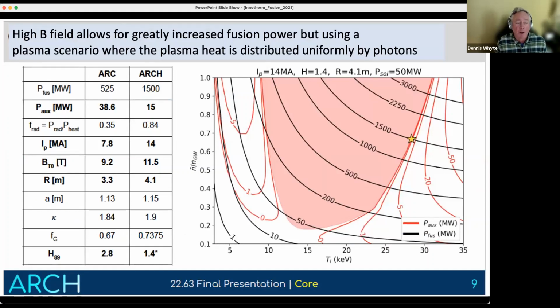Where we ended up was, there were some other things that happened in terms of the fusion design. We decided we had to eliminate any concentration of internal heating on the surfaces from the plasma removal, so we got rid of it. The way we got rid of it was that being able to access higher magnetic fields allowed us, very non-intuitively, to intentionally degrade the plasma confinement, such that all that alpha heating that I showed before is intentionally converted into photons and distributed uniformly and isotropically to the first wall of the device. This just shows that the plasma physics works. I'm not going to go through the details, but in the end, it showed that you could have this plasma be self-sustaining at 1.5 gigawatts of fusion power and need almost zero input power.